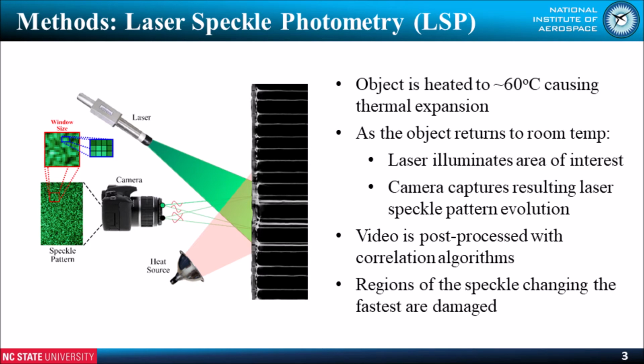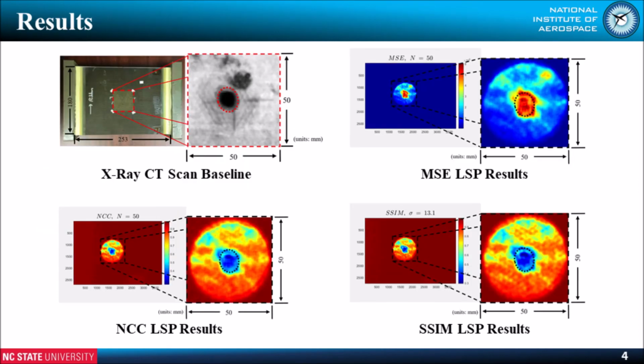speckle pattern to change. Damaged regions often contract faster than pristine regions, meaning that the speckle pattern near the damage will change faster than in the healthy regions. We leverage this by comparing the first frame in the video to every subsequent frame, looking for which regions change the most quickly over time. This change is quantified using post-processing image correlation algorithms, and regions which have the highest change or lowest correlation are most likely damaged regions. Here are the results.